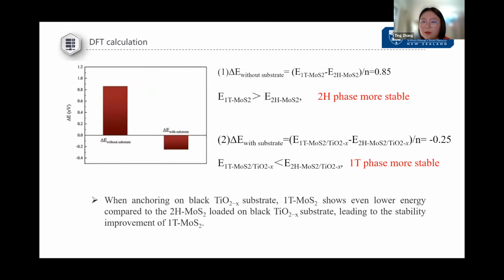To further analyze why the 1T-MoS2 stabilization can be enhanced during the reaction, we did the DFT calculation. We calculated the system energy of 1T-MoS2 and 2H-MoS2 without the help of substrate, and also the 1T-MoS2 and 2H-MoS2 with the help of black titanium dioxide substrate. After the calculation, we found that without the help of the substrate, the system energy of 1T-MoS2 is higher than the 2H phase. That means the 2H-MoS2 is more stable because it has smaller system energy.